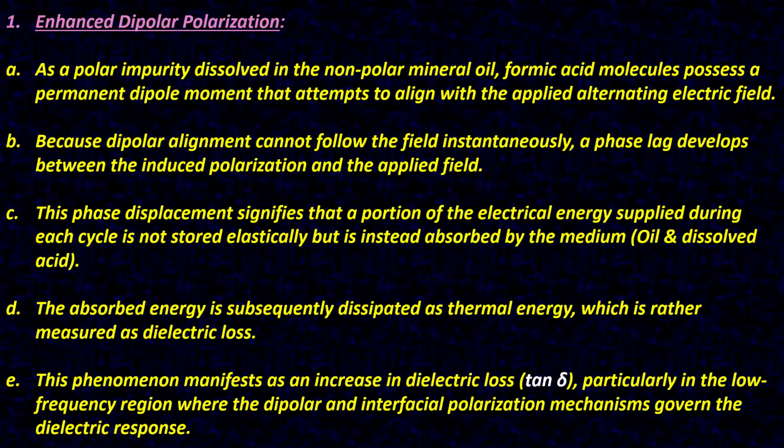The absorbed energy is subsequently dissipated as thermal energy, which is measured as dielectric loss. This phenomenon manifests as an increase in dielectric loss, that is tan delta, particularly in the low frequency region where the dipolar and interfacial polarization mechanisms govern the dielectric response.